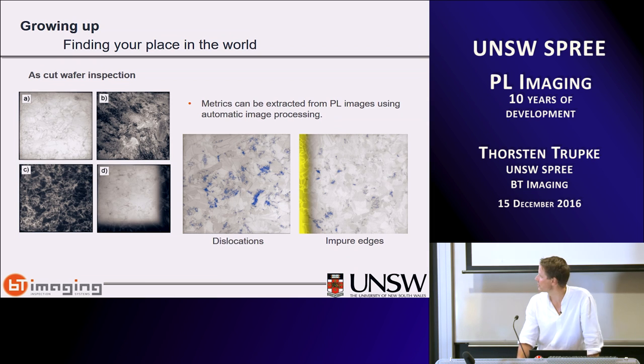And the features we see in the images are related, as you can see here, the black defects highlighted in blue here. These are structural defects in the multicrystalline wafers related to dislocations, and these have a very strong impact on the solar cell efficiency. The other type of defects here, highlighted in yellow from automated image processing, are related to iron concentration, which is often found in the vicinity of the edge or the corner of a brick. And again, these are detrimental for solar cell performance.